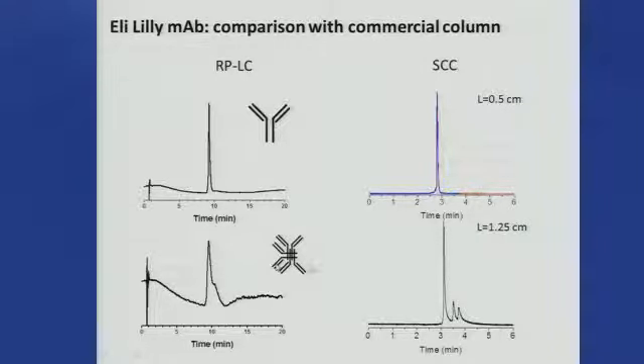Eli Lilly gave us this formula for how to coax this to make aggregates. And so you see the aggregate here, unresolved just as a shoulder. We have size exclusion data to give the mirror image of this, showing that it really did aggregate. And then in 1.25 centimeters, which is a ridiculously small distance, we get the monomer, the dimer, and the trimer resolved. And so now what we're doing is we're working on making the length longer and starting to put this into stainless steel columns so that people can collect fractions.